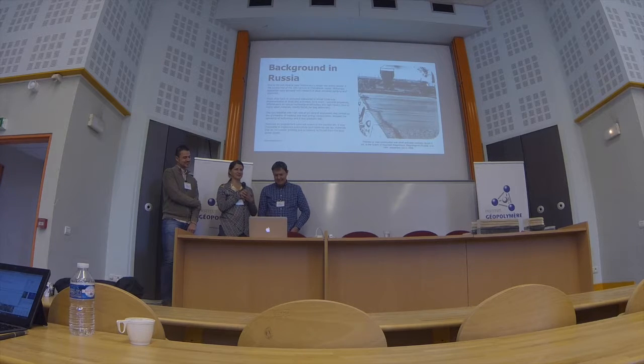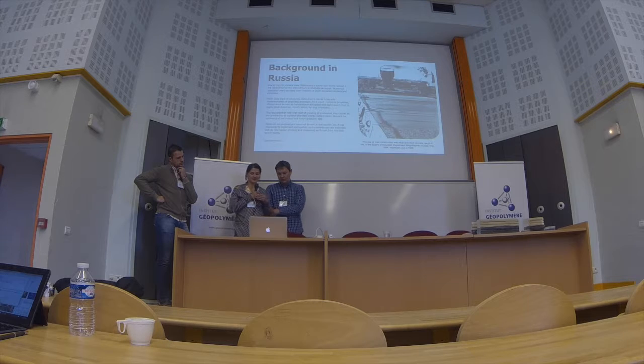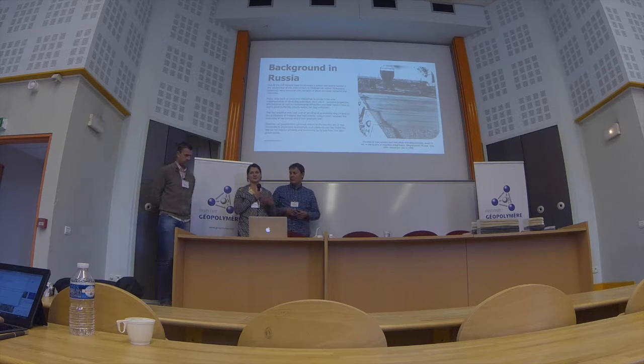A little bit of background from the Soviet Union. As you know, Glukhovsky had his school in Kiev of alkali-activated materials, and his school was very popular in our region because of huge deposits of metal waste, like granulated blast furnace slag, and a lot of scientists were occupied with alkali-activated materials, but they have their drawbacks. As we know, they have unstable properties, and also granulated slag is very hard to mill.